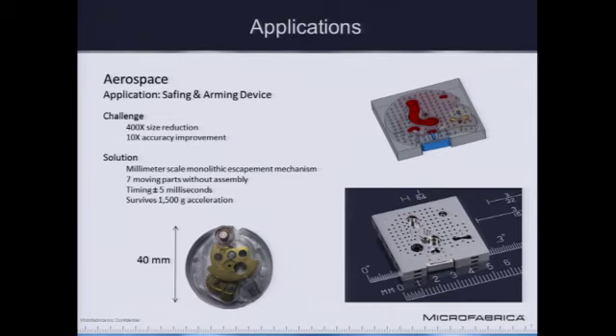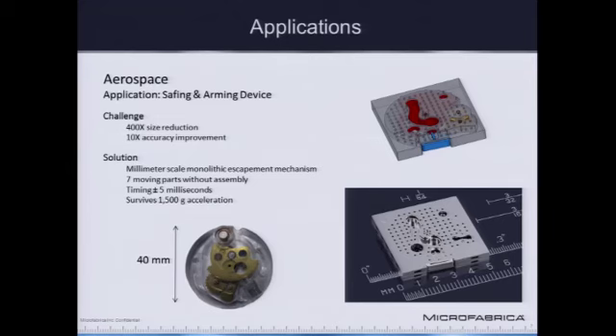And the goal was to reduce the size, reduce the volume by 400 times. You could pack more explosive in it, you could put more intelligence in this part, but also improve the accuracy of when it times. So improve the timing mechanism of this part. And really, this is almost like a little watch. It's a little escapement mechanism, 7 moving parts. So what we've been able to do is take this 40 millimeter device, shrink it down to about 5 millimeters in length, and about 700 microns in height. And what you see on the right, this CAD model, this is what the part looks like.